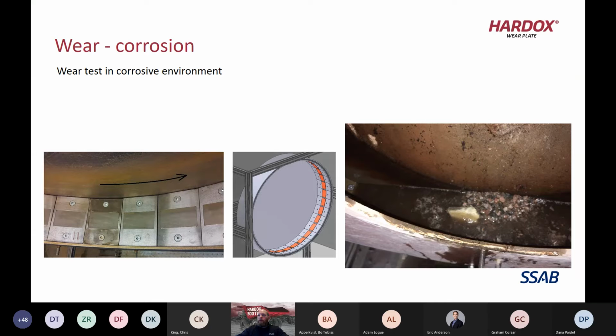Now in Sweden, in our R&D facility, we have what we call a drum wear test. Basically it's a drum where we load, I want to say it's like 27 or 30 samples into it. Each sample is milled to size and weighed prior to going into the drum. Each sample is mounted in the drum, and then they can load a different type of media.